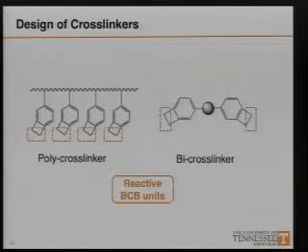Based on that chemistry, we have designed two types of crosslinkers. One is a polymer with benzocyclobutene pendant groups. In this crosslinker, we are looking for attachment of BCB groups on the same chain of polymer onto different nanotubes. In this way, the covalent crosslinks have been established.